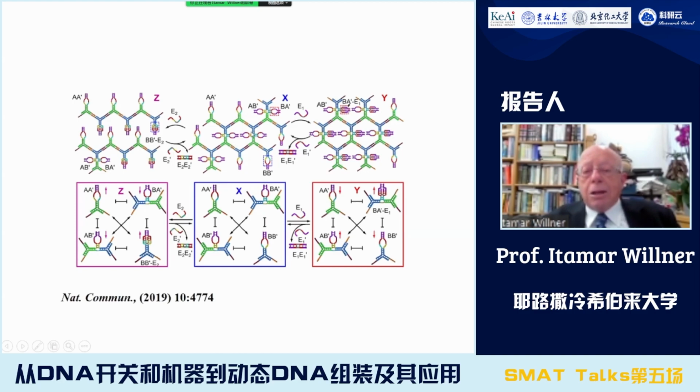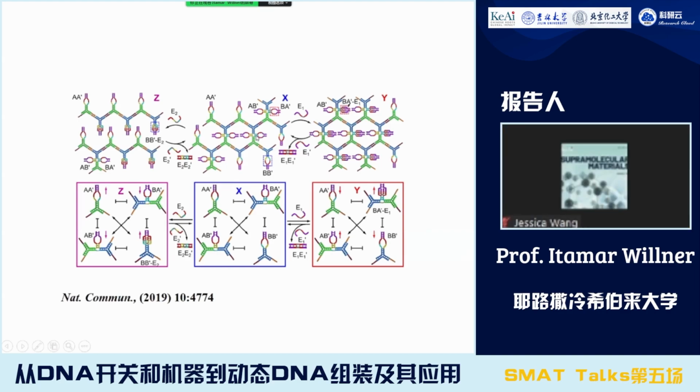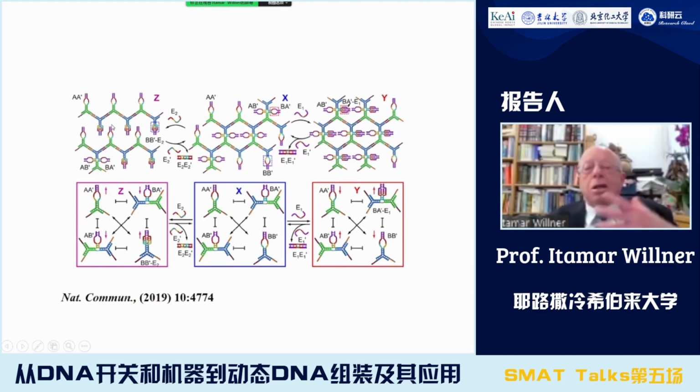More of the bifunctional bridging units will introduce higher cross-linking and a stiffer hydrogel. Lower bifunctional cross-linking units will generate a hydrogel of lower stiffness.